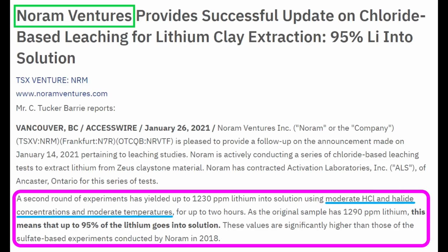Noram's test process extracted 95% of the lithium, which is better than the 40 to 60% lithium extracted by typical brine and hard rock processes. With all that said, Noram didn't explain the steps before and after the lithium extraction process, like whether roasting was used. So, take it with a grain of salt.